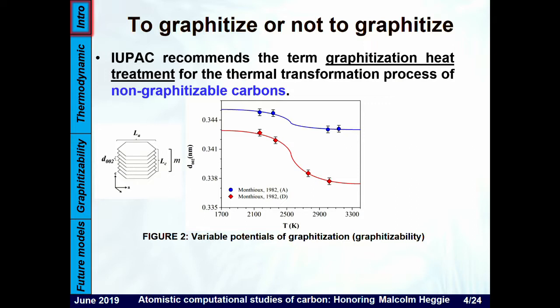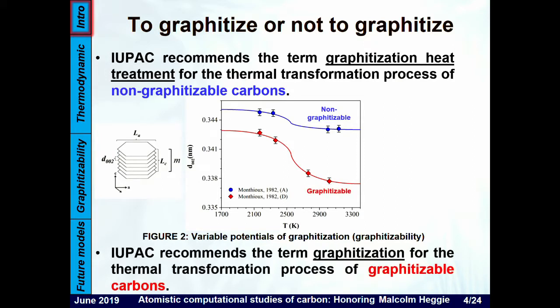There's a clear distinction to be made between graphitization heat treatment and graphitization per se. Graphitization will yield a graphitic carbon. Graphitization heat treatment will yield a non-graphitic carbon. So I know this is a little bit tricky, but it's important for the clarity of the presentation. So here, as I said, you have the graphitization heat treatment of a non-graphitizable carbon. And below, you have the graphitization process of a graphitizable carbon, which yields a graphitic carbon.